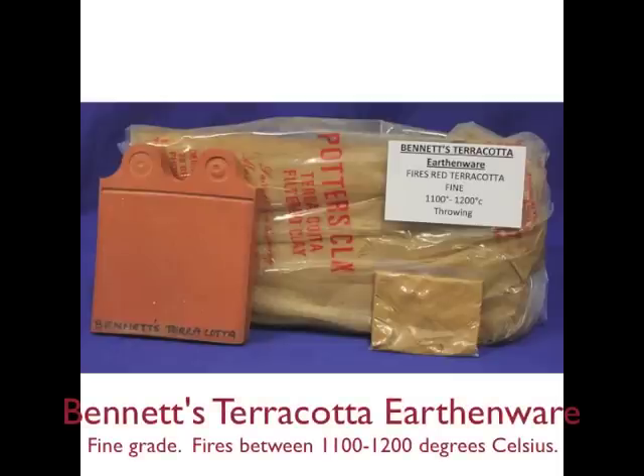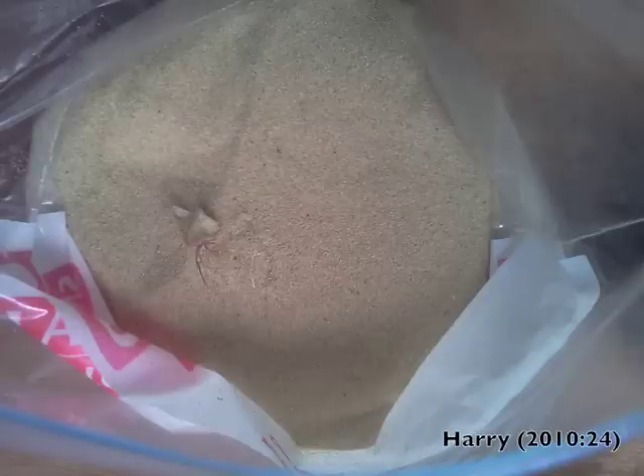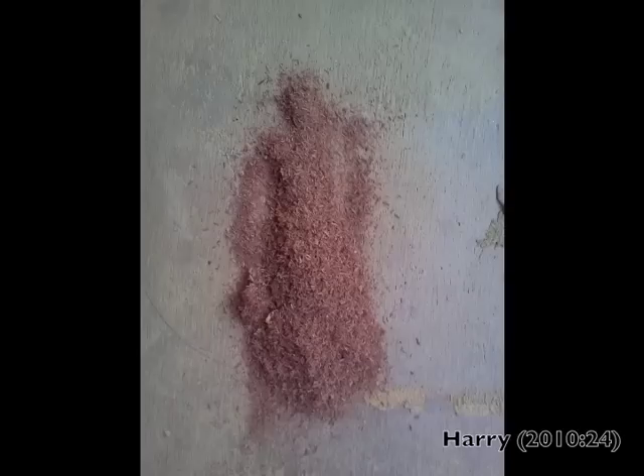The experimental vessels were constructed out of a fine grain commercial clay, and approximately 20% sand temper and 20% fine sawdust temper were wedged into the clay blocks.